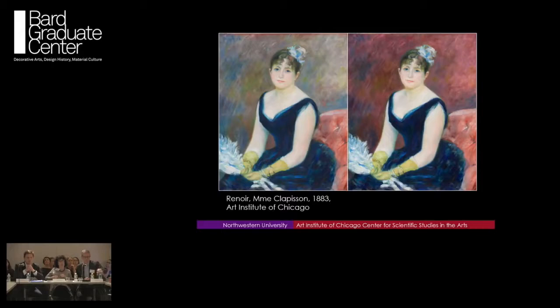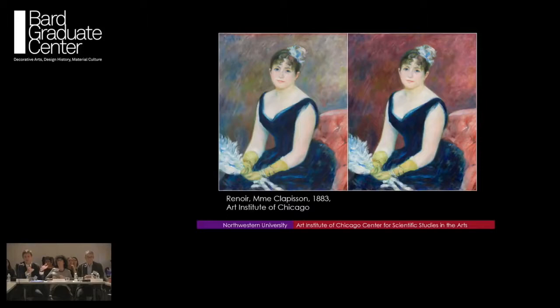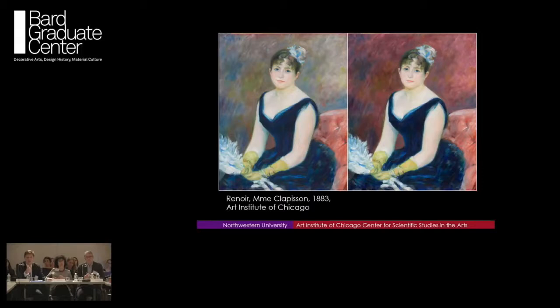The background of the Renoir painting has a gray-blue-greenish, anemic feel — it's out of color balance. Materials analysis reveals the change in color balance is due to eosin red, which has undergone a transformation from how it would have looked when first painted by Renoir. On the right we have a reconstruction — a plausibly reimagined surface — brought together using Photoshop and clever printing. This process of materials science reveals that the artist used eosin red, speaking to the agency of the artist and revealing new information about artistic practice at this time period.